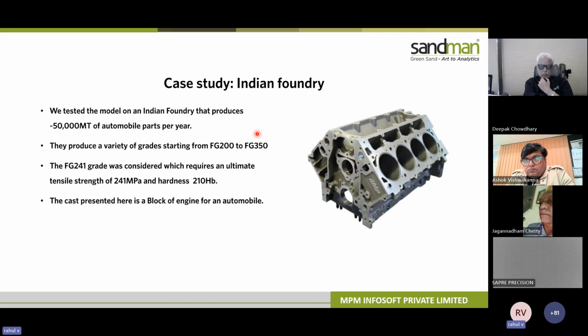So to test this out, we have done a case study on an Indian foundry, which produces almost 50,000 metric tons of automobile parts per year. This foundry produces grades anywhere from FG200 to FG350. And for our test case, we took a block component of grade FG241, which has a tensile strength of 241 megapascal and a hardness of 210 HB.